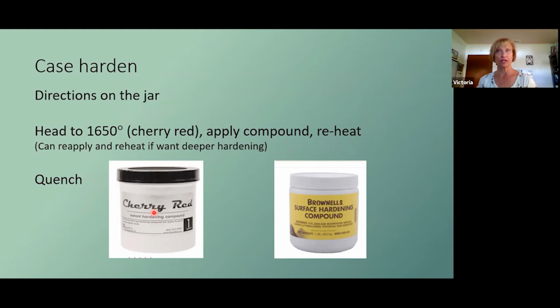You apply the carbon. When you quench this, that turns to gas, and that carbon penetrates your metal, giving you that hard outer shell. It should be wet when you're quenching, and you should hear a loud pop. If you don't, go ahead and do it again. Sometimes I'll heat it, apply, heat, apply more than once, and then quench, and then do it all over again. As long as when I'm done, I can test it with a file so that the file should be skating off it. That'll give you enough hardening on the outside to have a tool that lasts a little longer.